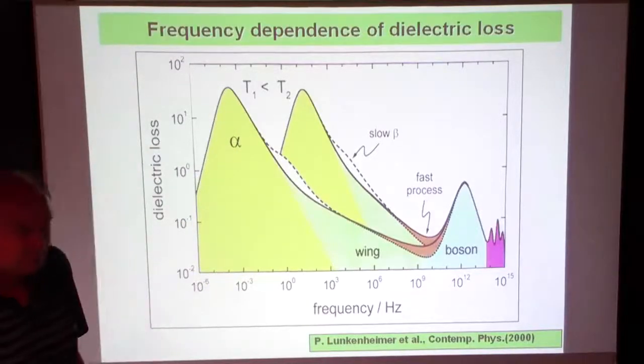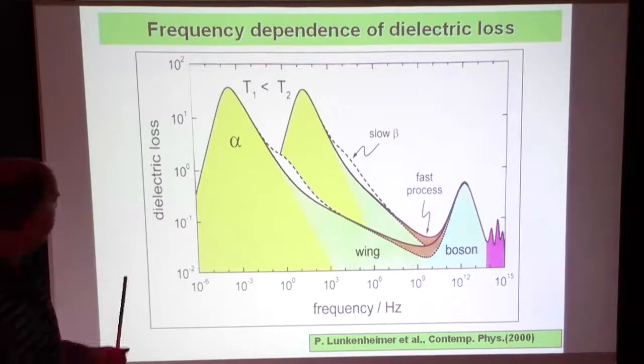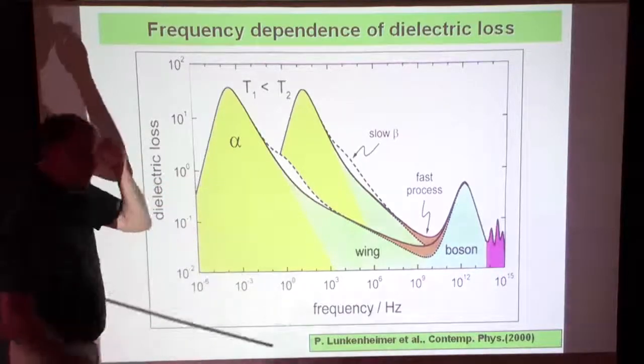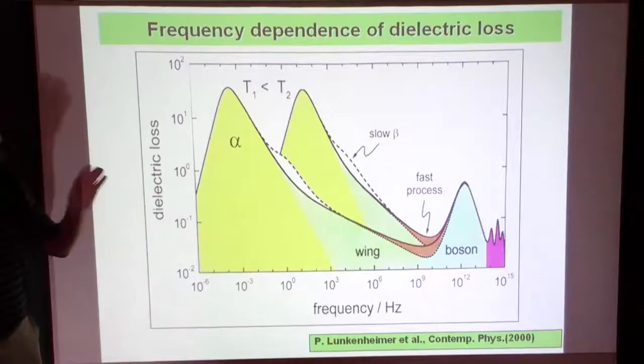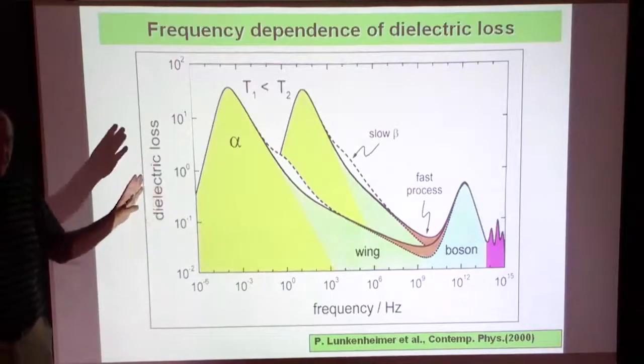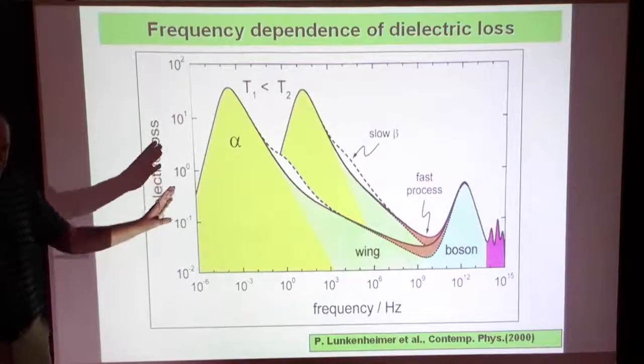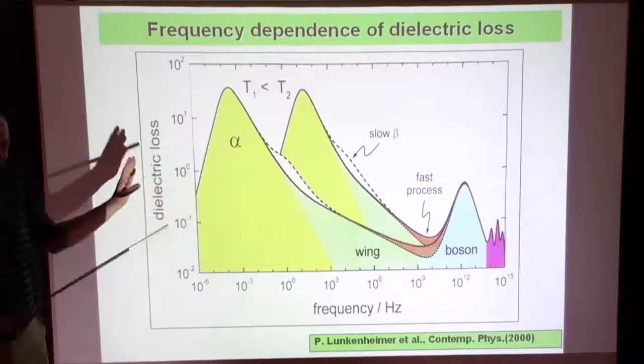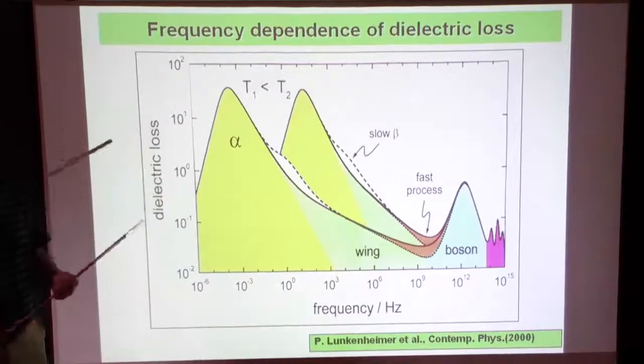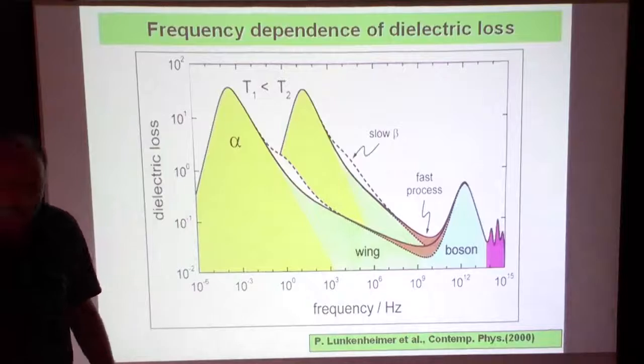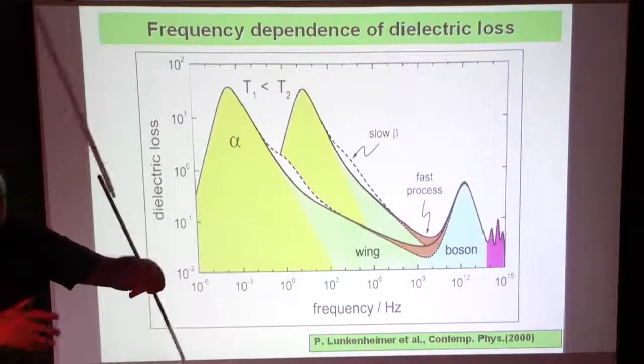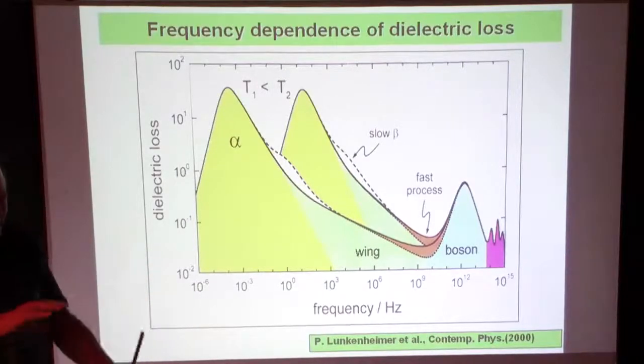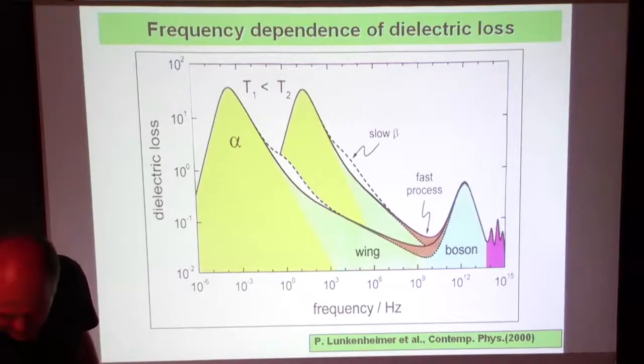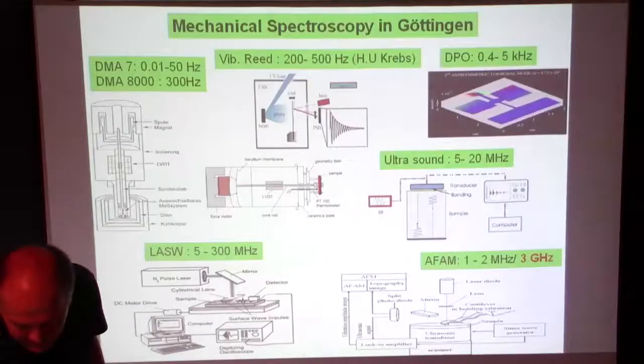But in the middle of the temperature range, you just showed us, you're vaguely where this little bump comes that you're calling slow beta. Yeah. We did measurements on polymers, and to show that the type of measurements we did mechanically and the electric measurements are the same. Okay, there are some little changes in how you excite the backbone of the polymer mechanically compared to what the dielectric measurements do, but that's a little detail.